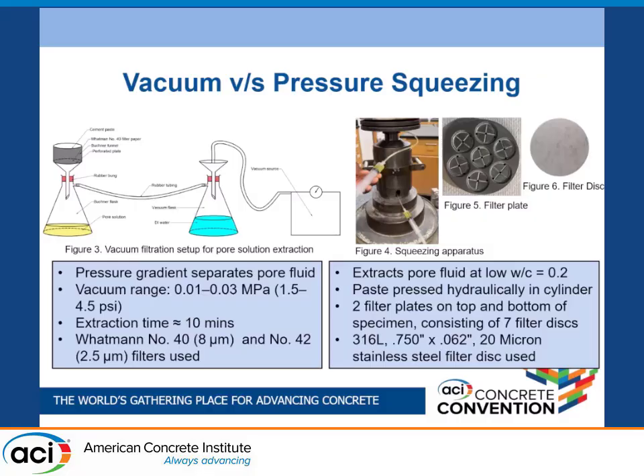We are not using gravity filtration because it is relatively slow. So we want to use vacuum filtration, and the vacuum range is very little, around 1.5 to 4.5 psi. The quantity of sample we extract: if we do 0.7, we are extracting about 70 grams of water out from 140 grams of the sample. The extraction time is approximately 10 minutes, and we stop when we feel all the solution is out and the paste is completely dry.